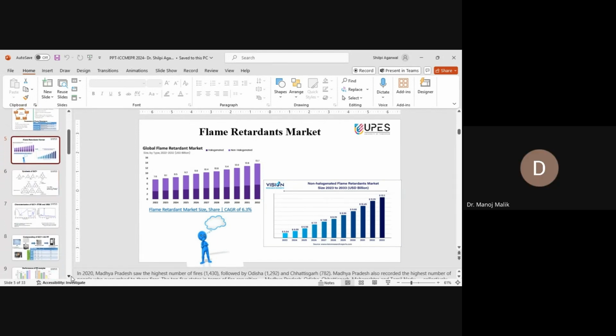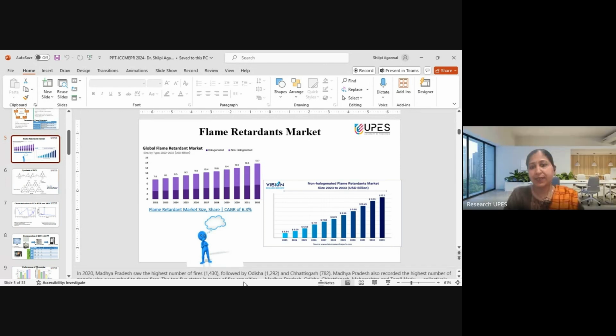Sure. Now, one more thing is there with the flame retardant. Many flame retardants are being used, as I told you, nitrogen containing, phosphorus containing. But the drawback is that when we use a single flame retardant in a polymer, we need high loading. Around 40 to 60% of the flame retardant we need to add to bring that efficiency. It means if we can use some synergist, which can reduce the loading of flame retardant, then it is a big step in this direction.